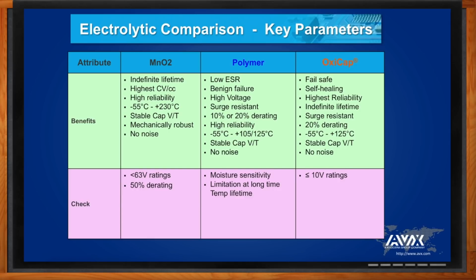And the Oxicap is a true fail-safe because there's no metal content and it's an oxide base. So you can't actually get a short circuit in an Oxicap. It will break down resistive. It's got great self-healing. It's the highest reliability for a commercial part. You only need 20% derating in this as well. Stable temperature and no noise. If we look at the things that you need to check, the tantalum, always bear in mind that 50% derating as a rule of thumb.